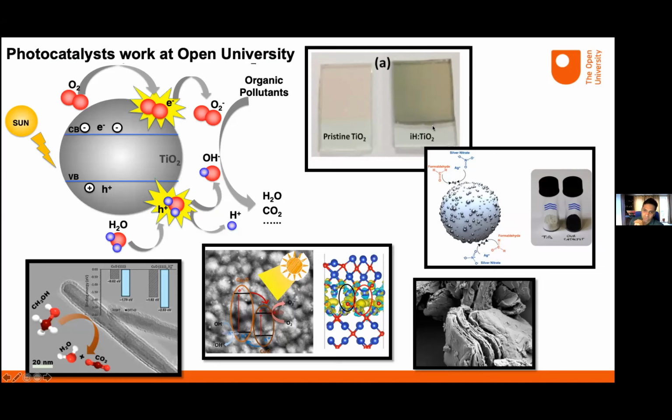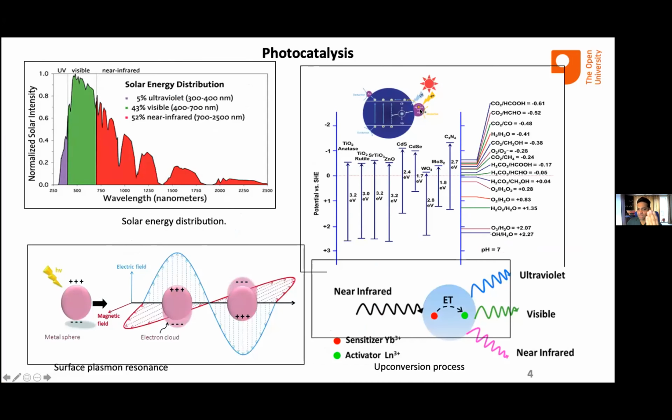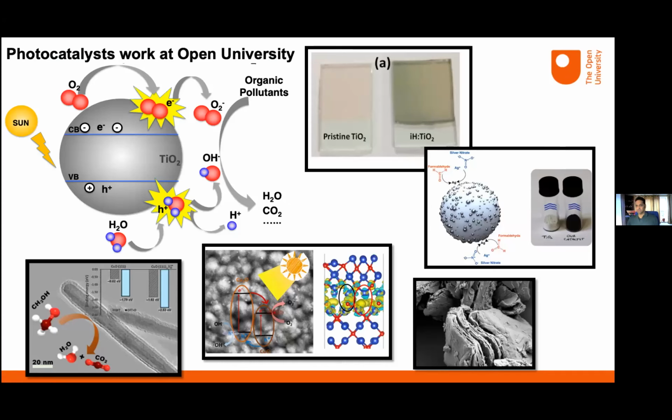The change of wavelength also happens, and this is because we are creating a Ti3+ state, which causes defects in the surfaces and enhances the oxygen vacancies. These oxygen vacancies push us towards a lower band gap and the higher visible spectrum. So we were able to get that.